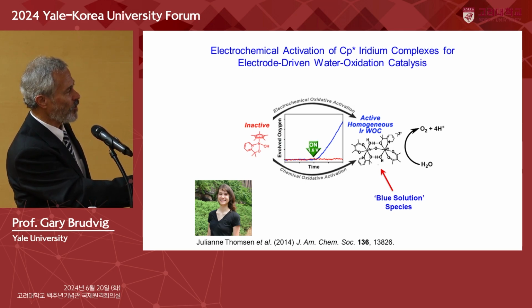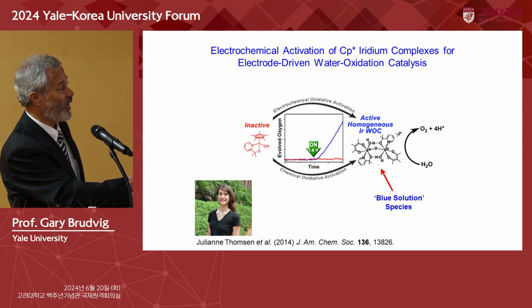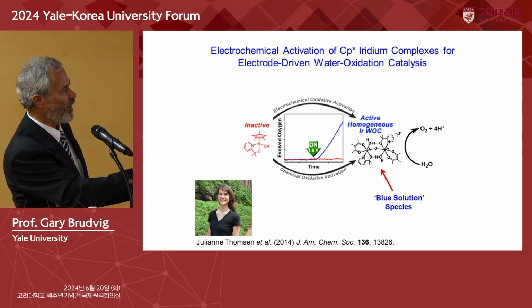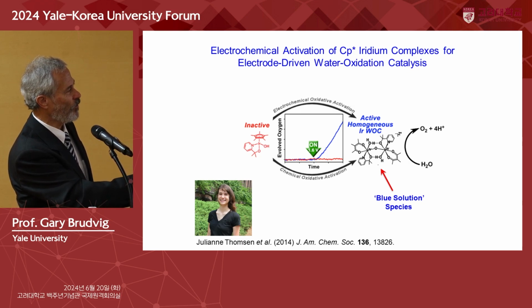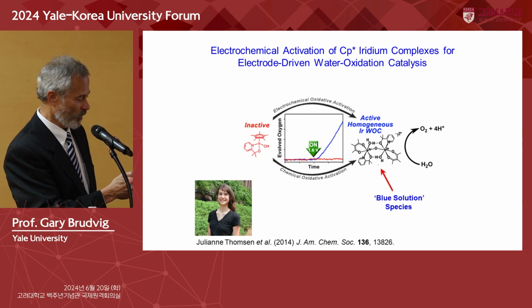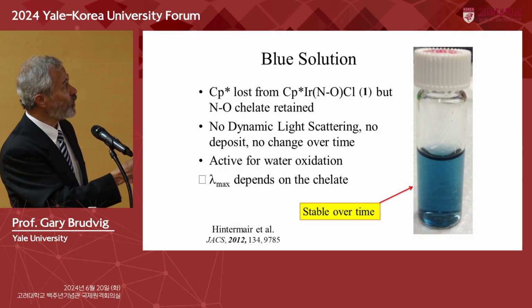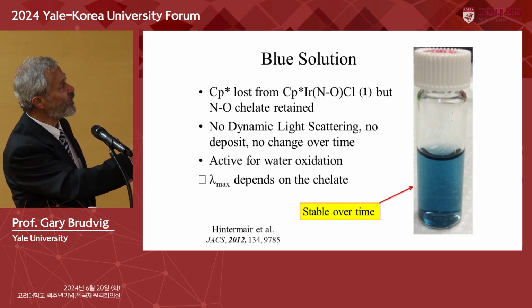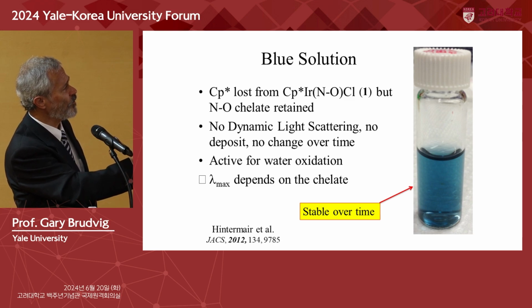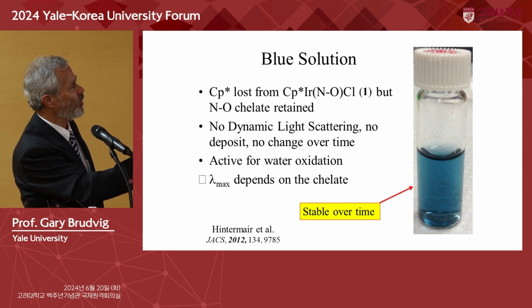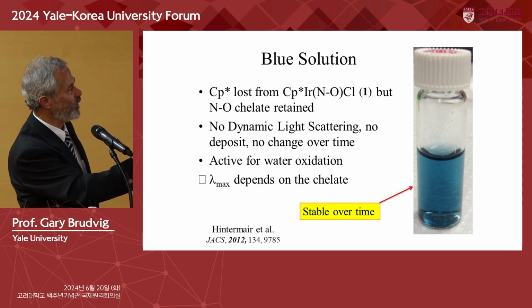And by either chemical oxidation or electrochemical oxidation we can form this iridium dimer, which is an incredibly good water oxidation catalyst. We call it our blue solution species. And this is just showing that this complex, if we turn on 1.6 volts, doesn't produce any oxygen, but the blue solution produces oxygen at a very high rate. And this blue solution is an activation from this initial precursor. The chelating group is retained. The pentamethylcyclopentadienyl is oxidatively lost.